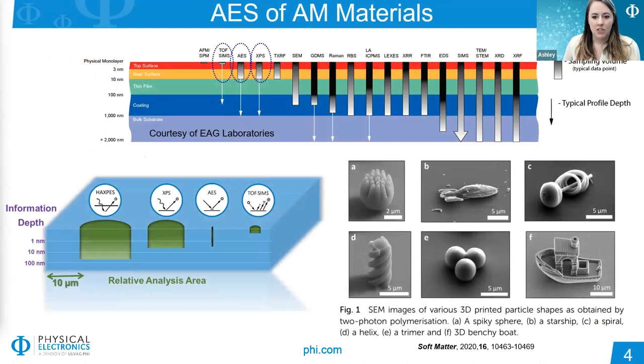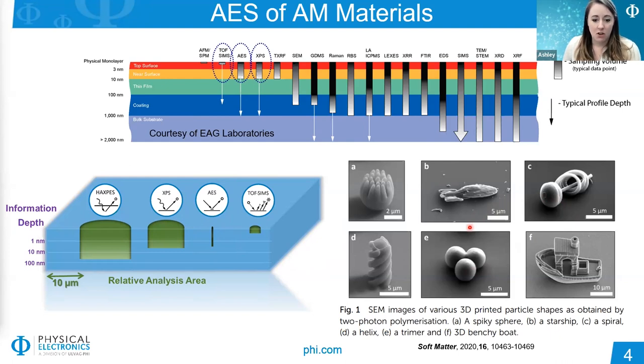So what makes Auger electron spectroscopy the ideal technique for analyzing these 3D printing materials? AES is extremely surface sensitive with an information depth of about two to five nanometers. Of the major surface sensitive techniques — Auger, XPS, and ToF-SIMS — Auger has the smallest spot size, capable of elemental imaging features as small as eight nanometers in resolution. Even for larger scale 3D printed objects, the layer-by-layer nature of 3D printing inherently introduces the need for micro and nanoscale chemical analysis, as precise control over layer thickness becomes critical.